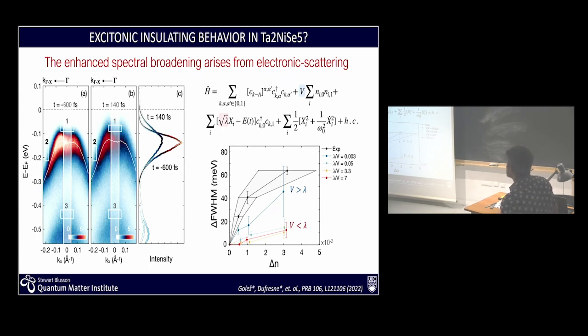electron scattering. And we can see that with the phonons, when the phonons are dominating, we are not able to come up here. In order to come up here, we really need the electron scattering to be dominating in the system. So we still cannot conclude that the transition is excitonic-like, but we can see that the electrons are really playing a key role.